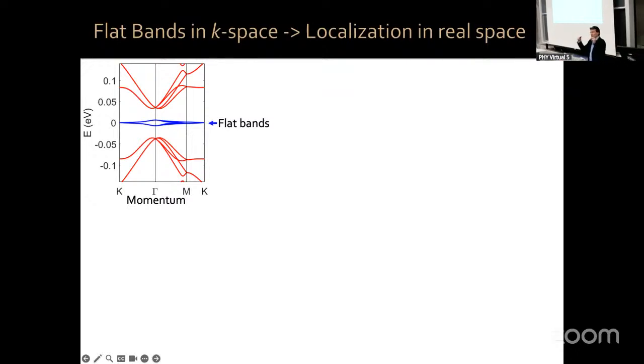These bands happen when you reach the flat band condition. They're not perfectly flat mathematically, there's a little bit of dispersion, but it's orders of magnitude less dispersive than the original graphene dispersion. These are the flat bands, the first Moiré mini bands. There are many such bands which come from the folding of the Brillouin zone when you do this superperiodic modulation. The other Moiré bands have much higher dispersion, getting closer to that of the original graphene dispersion.